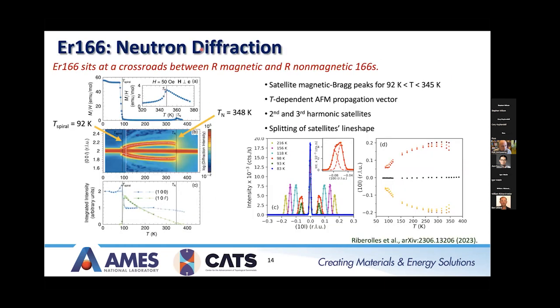So for the erbium-166, we looked at this with neutron diffraction using HB1A at HFIR. If we look over at the left panel here, the top panel shows you susceptibility data taken by Tyler Slade at Ames. You see two transitions. The first transition at high temperature here corresponds to the Néel transition. I'm going to call it the Néel transition, and then the transition down here at lower temperature, which is first order like, which is at about 92 Kelvin, I'm going to call that the spiral transition.